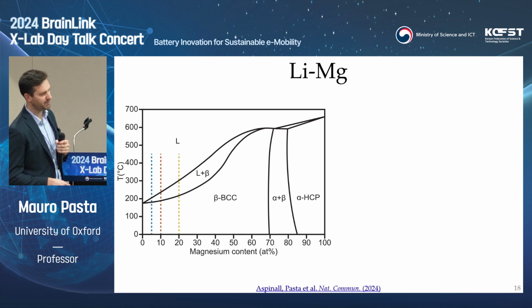When you pass the 70%, you enter this alpha plus beta region, where you have this alpha HCP, hexagonal phase of magnesium. The diffusivity of lithium in this phase is very slow, and in particular, this alpha HCP is quite slow. So what we can do in-house, we can make our own alloys by melt solidification in an inert atmosphere, of course. We made 20, 10, 5, and also, as I'll show you in a second, even below 5.